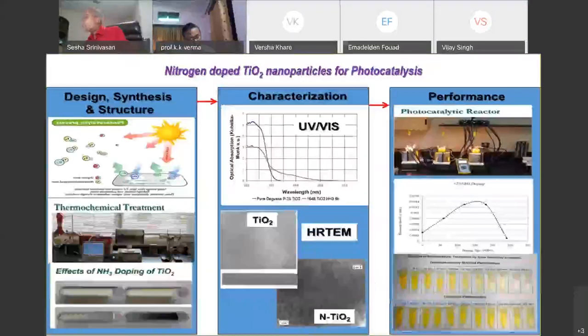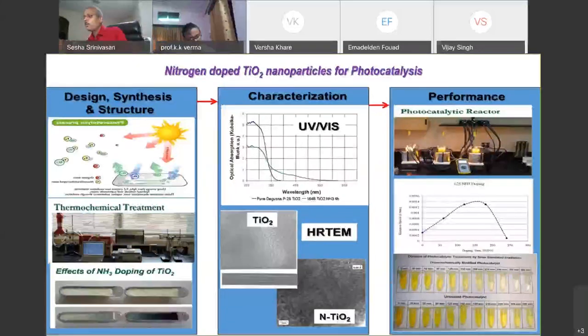The next project is about nitrogen doped titanium dioxide. We use the nitrogen coming from ammonia, so the nitrogen is doped on the titanium dioxide. Then we make it with a thermochemical treatment and use that to find out the absorption bands. The absorption bands are spreading up to 450 nanometers. That shows that it could be a visible light activated photocatalyst. What you see at the bottom of the figure, this is a photo batch reactor, with the untreated and treated photocatalyst. You see the water treatment is very successful in a few hours.